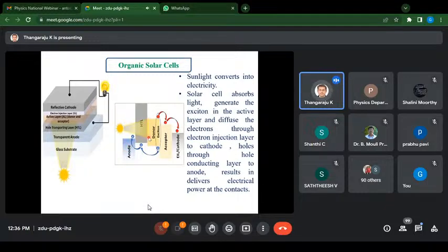And hence, in the organic solar cells, you can see that when the light is falling on the donor through this transparent anode and the hole transporting layer, the light energy is greater than the optical band gap of this donor molecule. So the exciton would be generated, and the exciton generated would be diffused to a certain length. Within that exciton diffusion length, it will get dissociated, and the dissociated charges would be collected by the electrodes, which will give the electrical energy for external usage. So this is how the organic solar cell works.